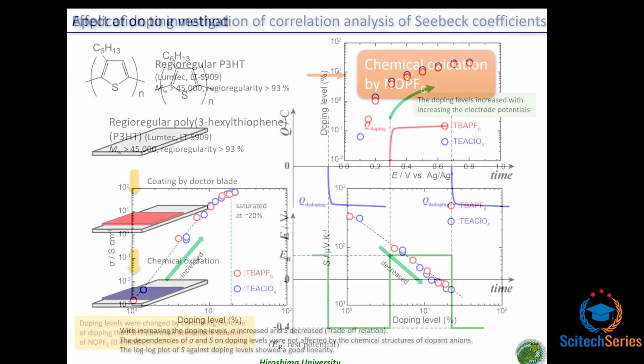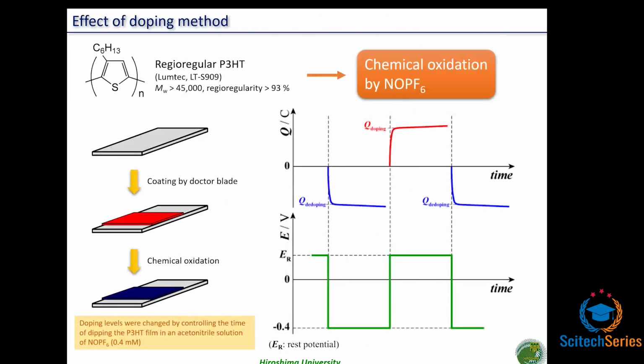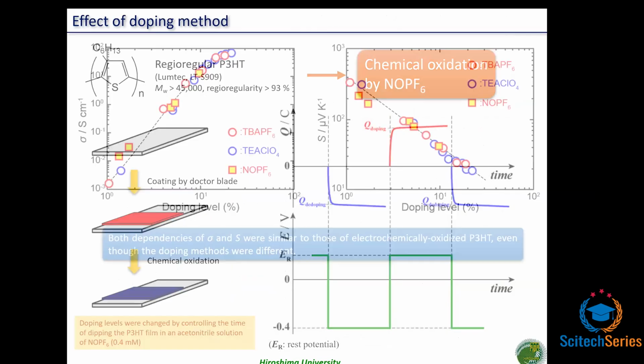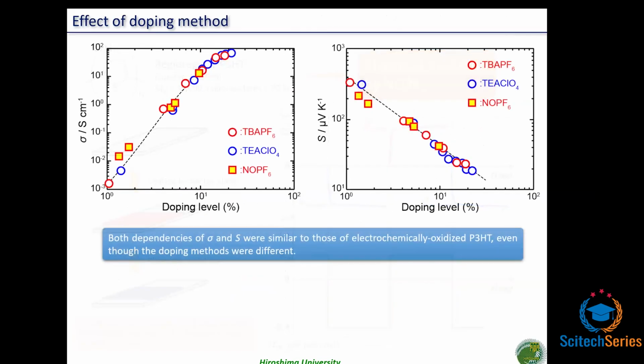In order to investigate the effect of doping method, P3HT was chemically oxidized using nitrosonium hexafluorophosphate. The doping levels were changed by controlling the time of dipping the P3HT film in a solution of NOPF6. The doping level of chemically oxidized P3HT films was estimated by PSC method. It was found that both dependencies of the electrical conductivity and Seebeck coefficient against the doping levels were similar to those of electrochemically oxidized P3HT, even though the doping method was different.